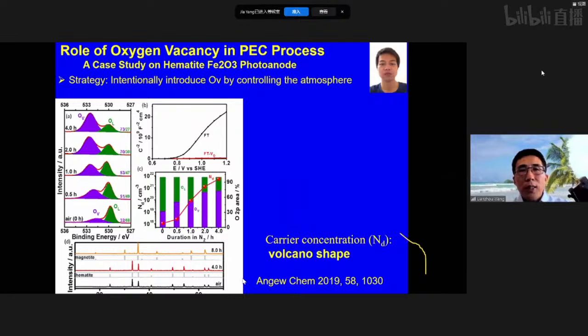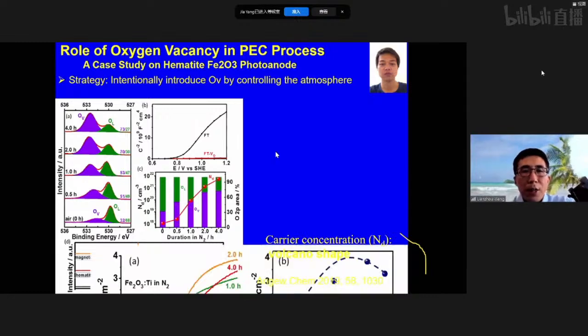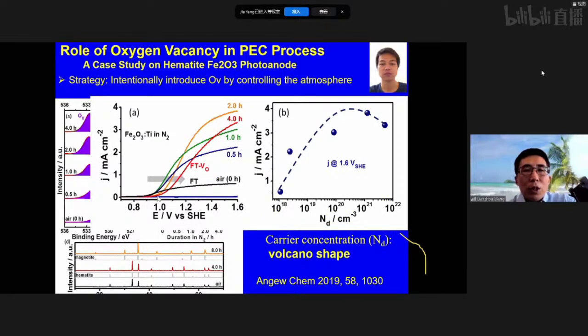In this case, we chose another narrow band gap semiconductor, iron oxide, as an example to showcase the role of the oxygen vacancy. We intentionally introduced different contents of oxygen vacancy in the iron oxide photoelectrode. There have been a lot of earlier studies on oxygen vacancy, and the commonly accepted role is that oxygen vacancy can certainly help increase the bulk transport of the charge carriers. We also found similar trends.